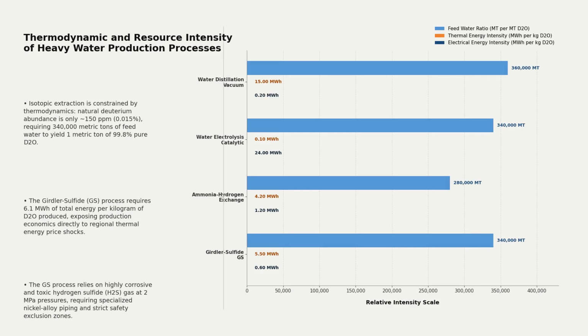Synthesizing reactor-grade heavy water is governed by severe thermodynamic constraints. Natural deuterium abundance is only 150 parts per million. Extracting 1 metric ton of 99.8% pure heavy water requires processing 340,000 metric tons of feed water. This low concentration makes the extraction process highly energy-intensive. The dominant Girdler sulfide process requires 6.1 megawatt-hours of total energy per kilogram of product. This high energy intensity exposes production economics directly to regional thermal energy price shocks.